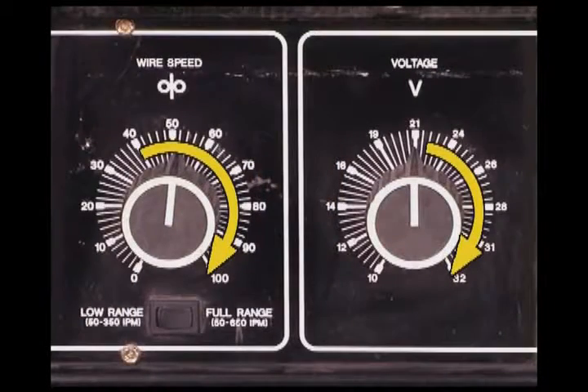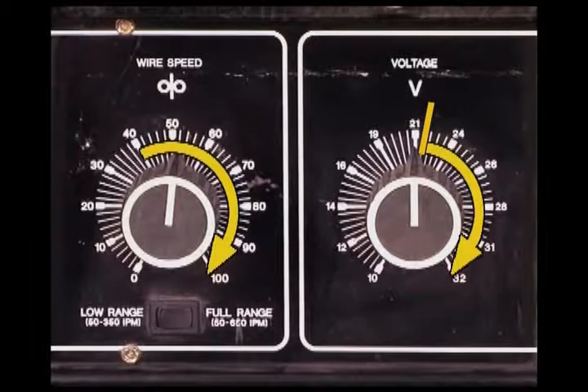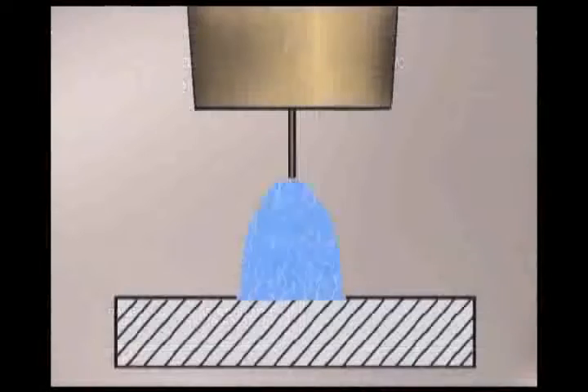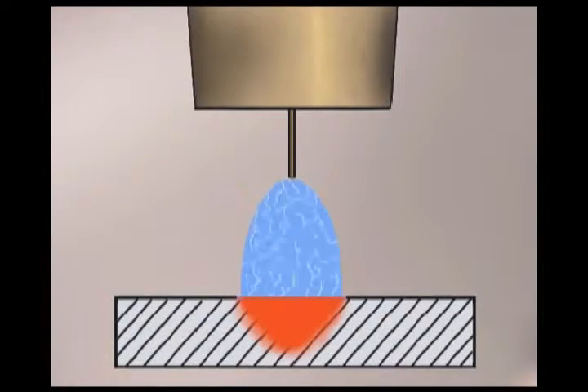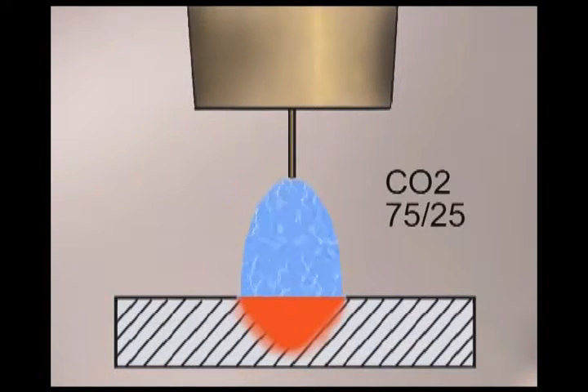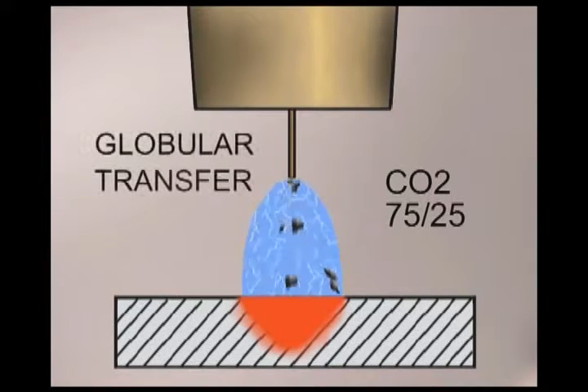In situations where better penetration or more weld buildup is needed, the voltage and wire speed can be increased. At a certain point, around 22 volts, the wire can no longer overcome the heat of the arc, and you have an open arc. It's on all the time. Hot gases create a constant arc stream that melts the base metal. With a carbon dioxide or 75-25 shielding gas, the filler wire transfers across the arc stream in molten globs. This is called globular transfer and produces deep penetration and good filler to base metal fusion.